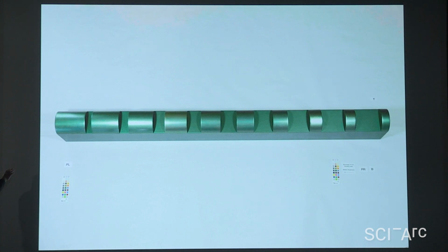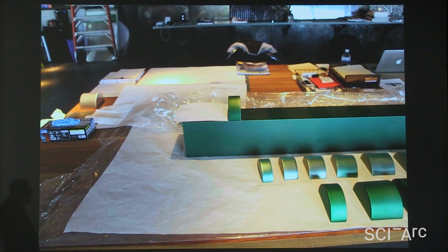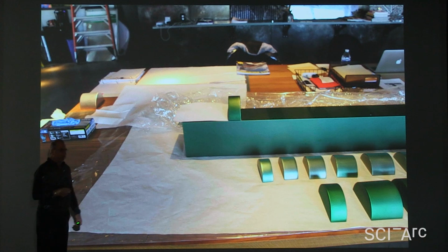You can't really see the fade in that picture. But we analyzed the surface. We want to know what the base metal is, so this is very close up, looking at we measure the depth of the anodized that was done on them, because if we're restoring a piece of art, we really can't adjust that surface. But Donald Judd, when he worked on this particular one, the information was that it was gold. It was a golden color. He didn't like it, and he had it re-anodized green.